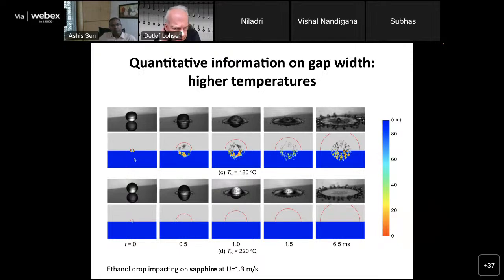So it also depends on the impact velocity, of course. The higher the impact velocity, the more you force your liquid towards the substrate. But it is in the range of milliseconds, and then within milliseconds, the equilibrium can establish. Okay, thank you.